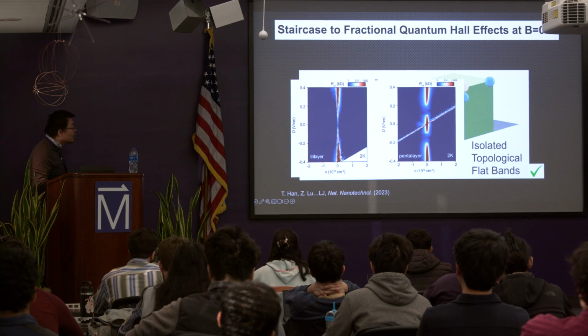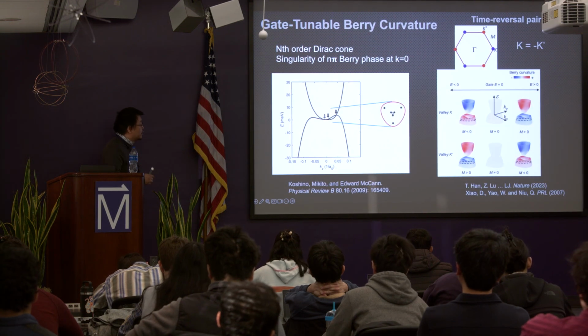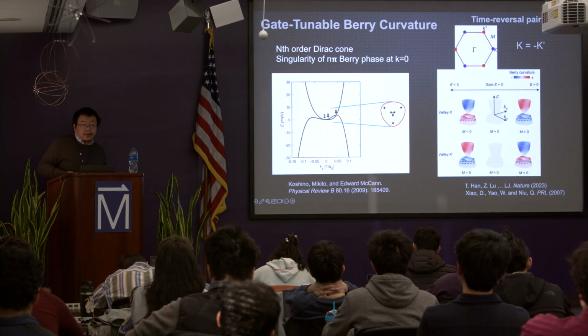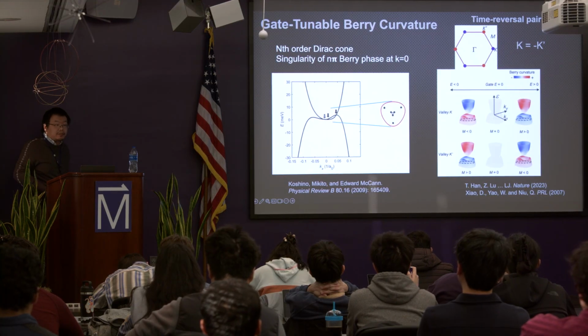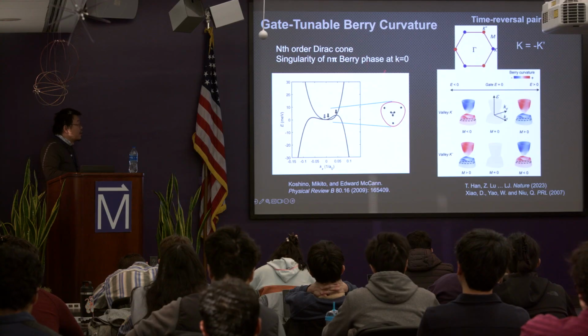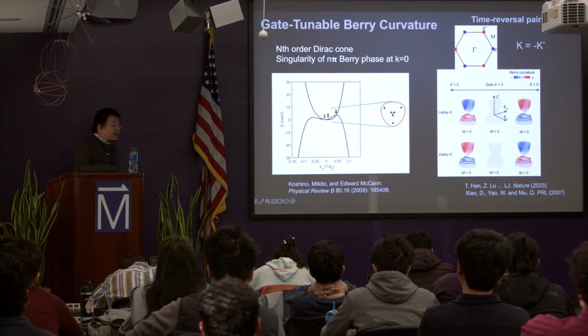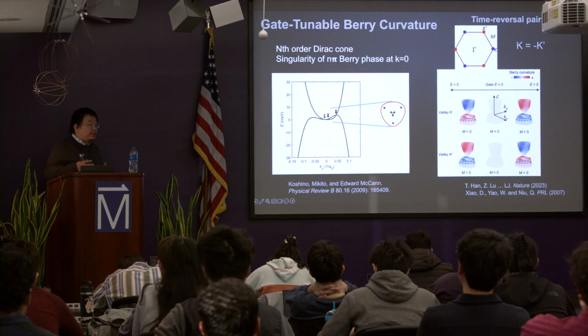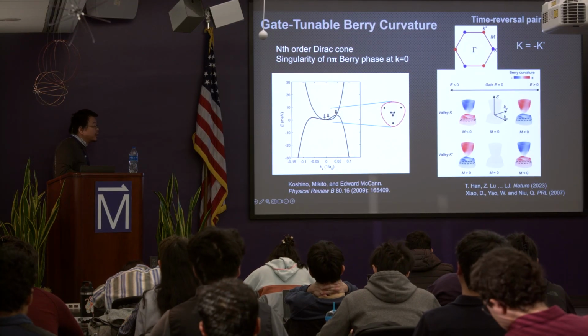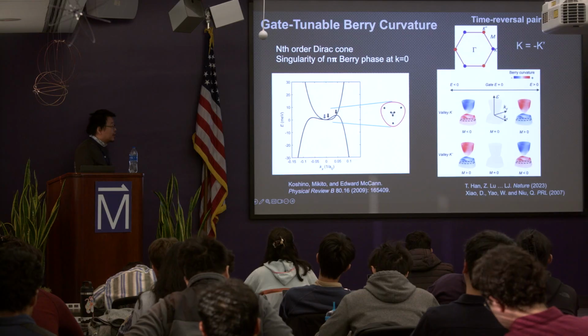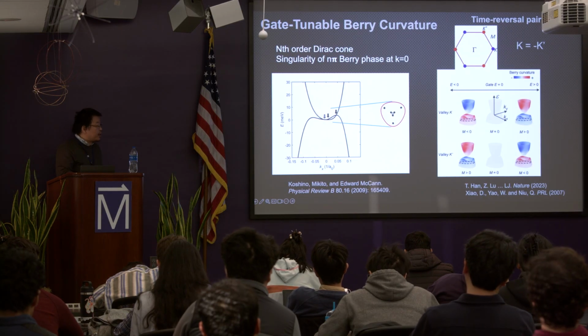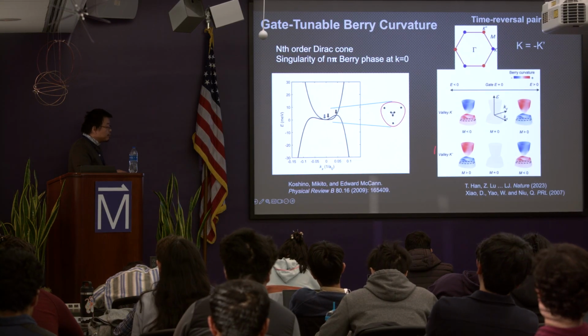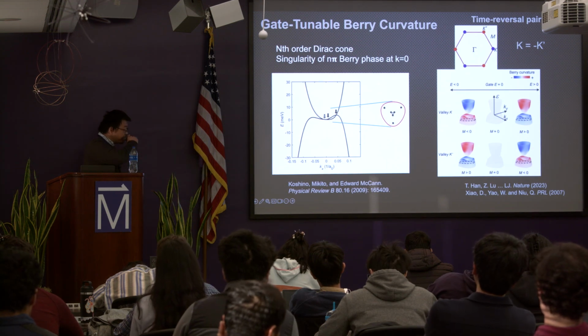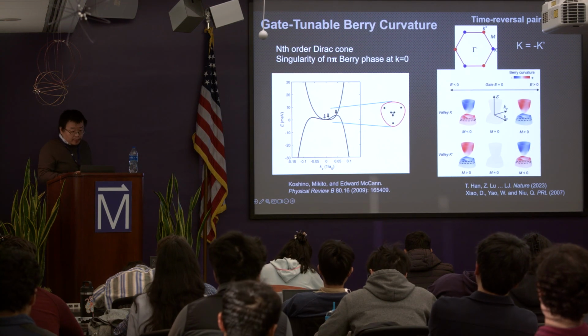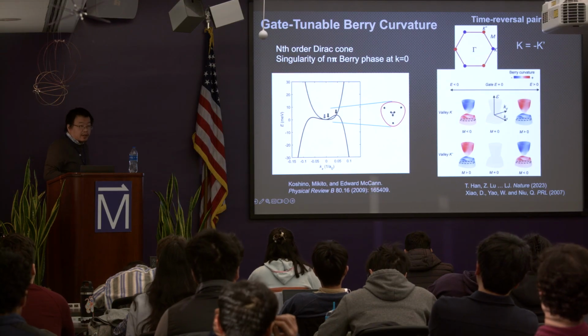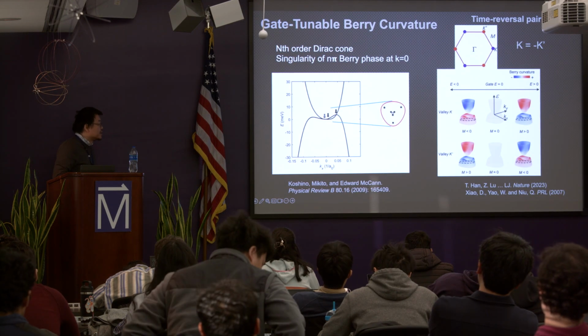Yeah. So okay, you have the flat bands, and actually graphene is also a topological material, right? In monolayer graphene, you have a pi Berry phase, and if you have n layers of graphene, you have an n pi Berry phase. And if you apply an electric field to open up the band gap, you expect the Berry curvature will concentrate around the band opening area, and by tuning the electric field and the doping, you can selectively tune your Berry curvature. So yeah, then you're probably going to expect something non-trivial in terms of the topology.